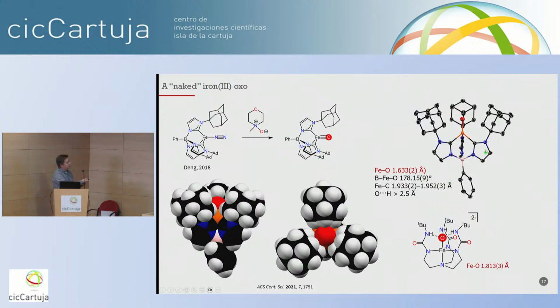And the crystal structure, again, is shown here. So you notice that the adamantyl groups are really, really big. The oxygen atom here is really hidden away in this pocket. There's no evidence of any hydrogen bonding from these adamantyl ligands to the oxo ligand, and so consequently the iron-oxygen bond length is much shorter than in the Borovik complex here. So we really think we have a true metal ligand multiple bond here that's not stabilized by anything else but metal ligand bond interactions.